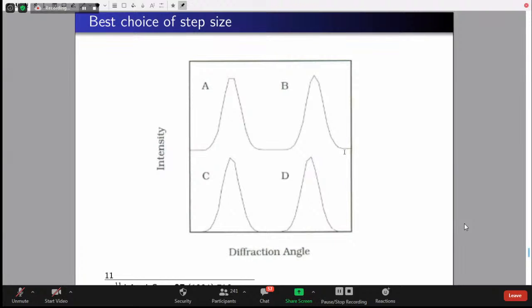And the second point is acquisition time. Usually for every step, they will give 1 second, which is in no way sufficient. So what I usually do is take the prominent peak, which will span around 3 degrees, and do 3 scans with different acquisition times: 1 second, 3 seconds and 5 seconds. Every time you increase the acquisition time, the intensity increases, and the definition of the peak is very different. In these 3 small scans of one single peak, you will find the best possible setting, and then you can use it for the entire spectrum and get a very good spectrum.